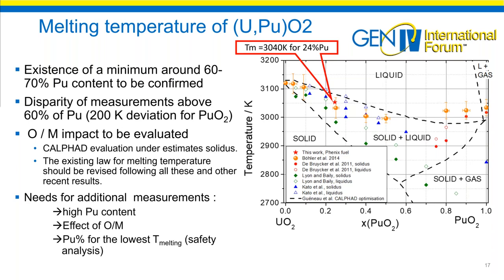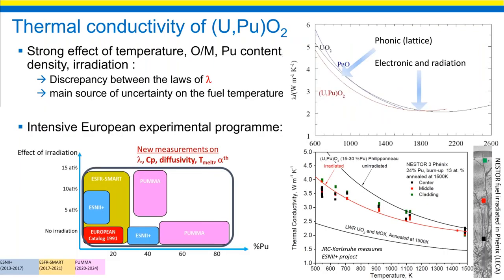We need additional measurements, especially for high plutonium content, also in order to check the effect of the stoichiometry. And we need to evaluate the plutonium content for the lowest value of melting temperature. This is for the safety analysis. So the next slide, please, on the thermal conductivity.